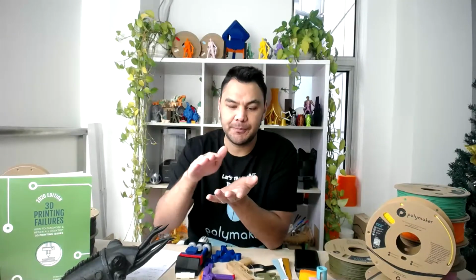And the last one is surface contact. Obviously, if you have more surface contact between one layer and the other, then you have a higher probability of creating entanglement between the two layers. So you can increase the extrusion width of your outer shell, or the whole print if you want. If you have a 0.4 nozzle, depending on your hardware, just force your printer to extrude at a 0.5 millimeter width, and you will start to have much stronger layer adhesion as well.